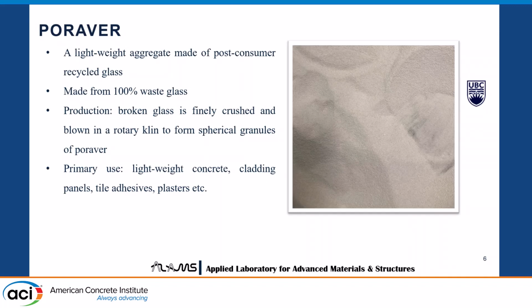Now, what is poraver? Poraver is the aggregate that we are using for our GFRC. It is a lightweight aggregate, as I have mentioned. It's made from post-consumer recycled glass, and it's actually made from 100% waste glasses. So the glass granules, which are not further used for producing new glass, are used for making poraver. Regarding the production process, the broken glass is first finely crushed, and then it's blown in a rotary kiln at a higher temperature, which forms the spherical shape of the poraver granules. And again, poraver is used basically for lightweight concrete and cladding panels. Sometimes it's used for plasters and also tile adhesives.